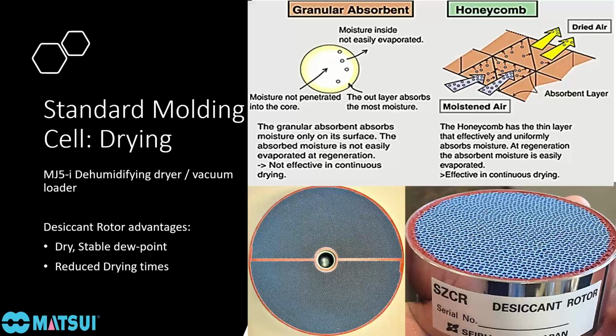We also use a flat desiccant surface compared to a round desiccant bead. The desiccant rotor is a substrate with the molecular sieves bonded or baked to it, like a corrugated shaped form. The flat desiccant surface allows us to have a higher air to desiccant ratio, so we can pull more moisture out of the air as it passes through compared to a round desiccant bead. Imagine if you spilled some coffee or water on a table, you would use a flat paper towel to soak up that moisture as opposed to a round sponge because the absorption would be much better.